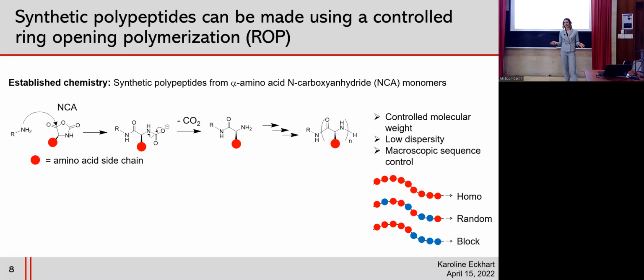There are a few different ways that you can make a synthetic polypeptide, but the way that I'm most interested in is through a ring opening polymerization of an N-carboxy anhydride monomer. This is a type of cyclic amino acid monomer called an NCA, and this can be polymerized in the presence of a nucleophile, for example, a primary amine. And in this polymerization, the primary amine attacks the anhydride of the NCA, which causes ring opening. And this molecule decarboxylates, releasing a molecule of CO2 and regenerating this primary amine end group, which can then propagate more monomer. And the result of this is a synthetic